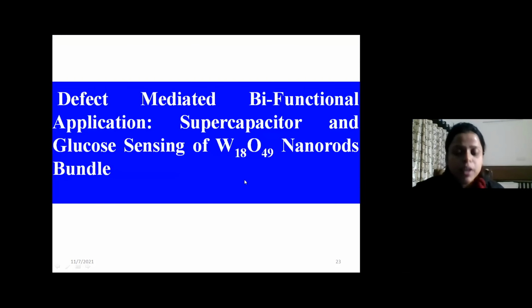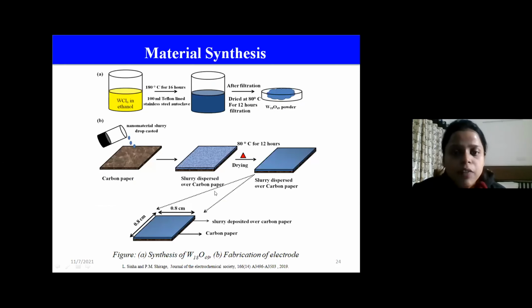Now another material that we have selected is tungsten oxide, a transition metal oxide. In tungsten oxide, we have created a defect, that is oxygen vacancy, so it has become W18O49 nanorods. Again, we have used the solvothermal method for the synthesis of the nanomaterial, and the same process for the deposition of this nanomaterial over the carbon paper electrode.